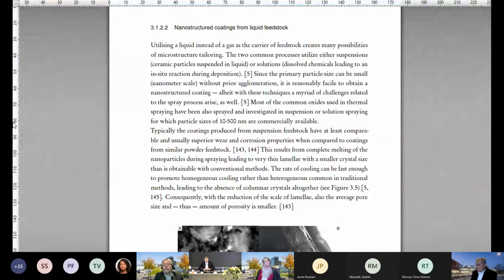Well, yes. If they're large agglomerates of nanoparticles, they start to melt, the particles would start to melt from the surface. And probably there we wouldn't have a nanostructure soon after. But inside the particle, so actually often when we find nanoparticles in a coating, it is unmolten particles that are embedded in the molten matrix of coating. And in these cases, for example, in solution precursor spraying, when the nanoparticles are formed in situ, in the flame or in the plasma, then I think they are reasonably isolated. And for the ones that are not, they have less time to melt.